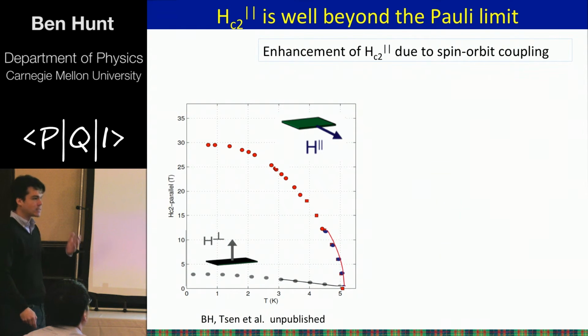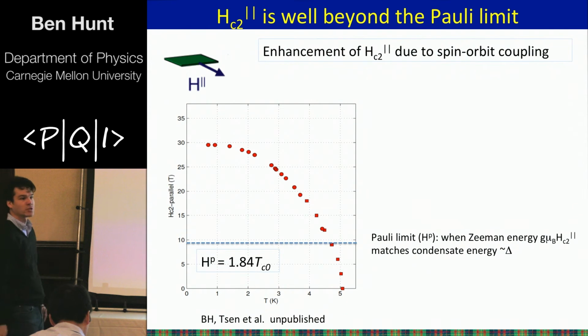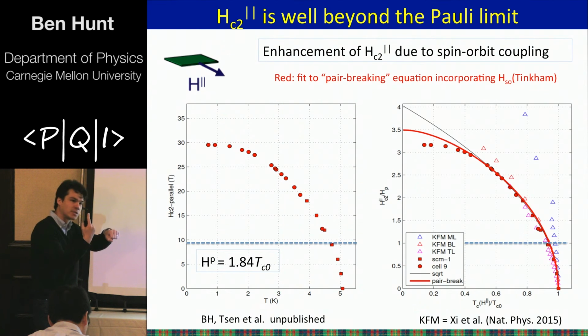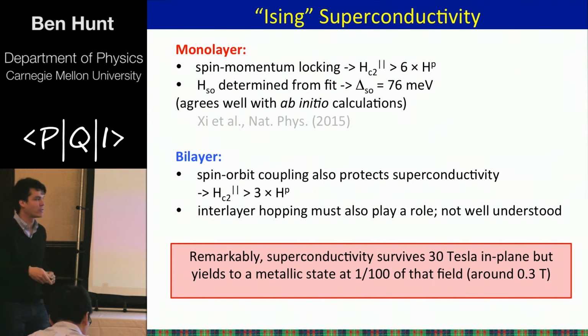That's actually quite a remarkable thing, considering for experts that the Pauli limit is down here. The Pauli limit is what you would expect from a naive picture of spin flipping in a 2D superconductor. So in our system, the superconductivity actually survives much, much higher than the Pauli limit. I don't really have time to go into why that is. But the takeaway message is that the superconductivity in our 2D system survives 30 Tesla in plane, but it yields to this metallic state at 1/100th of that field, so around 300 millitesla.